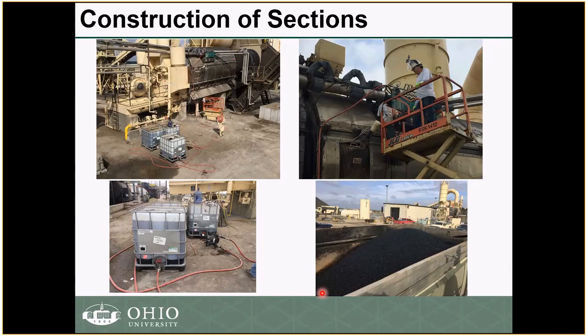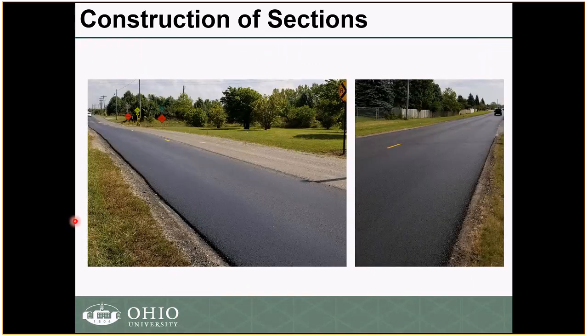Those pictures that I'm showing here are how the rejuvenators or recycling agents were injected. In this project, they were injected into the asphalt binder just before the asphalt binder went into the drum. You can see the tanks for the different rejuvenators, and they were pumped through the foaming device or the foaming hose, which is where it was injected. Again, there were really no problems in terms of the production and the use of recycling agent. Those are some pictures taken at the asphalt plant to document that. Those are pictures of the sections just after compaction, directly after construction. Again, you can see that there was no problem.